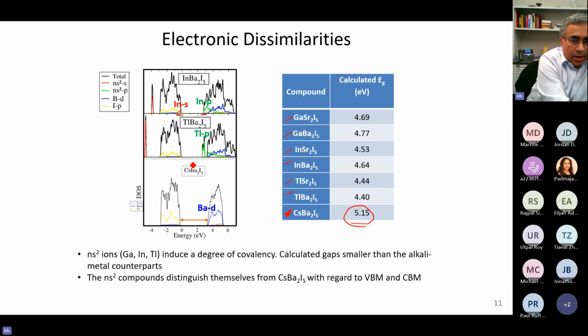In case of thallium, you have thallium P states right there, and then mostly iodine P states will be here. In this case also you have iodine P states. In indium barium iodide, the top of the valence band will be mostly iodine halogen P states. However, in case of indium, you also have some mixture of indium s states as well. In case of thallium, you have mostly iodine P states near the top of the valence band right there, and thallium P states near the bottom of the conduction band right there.